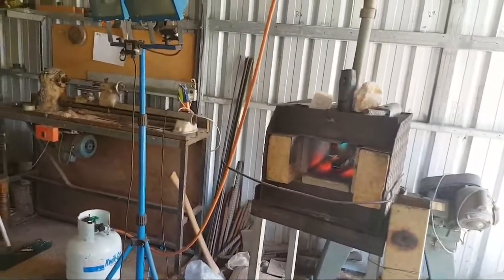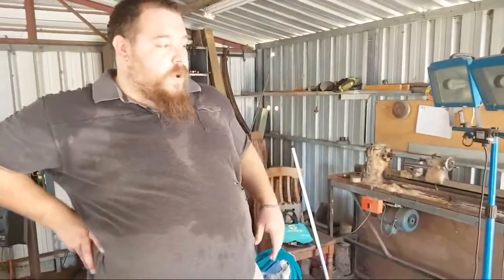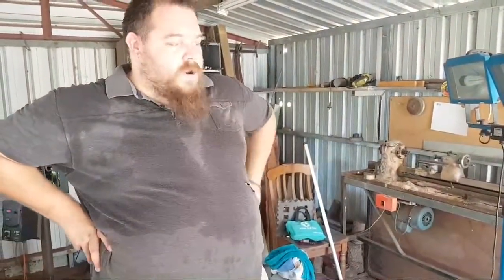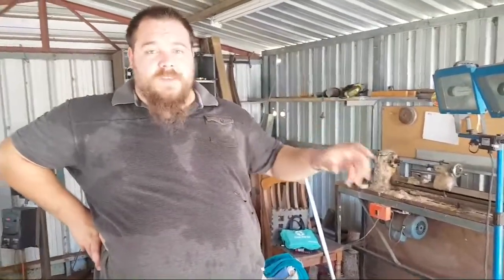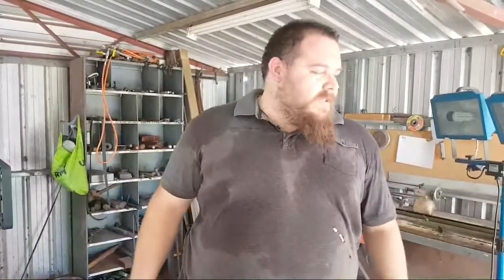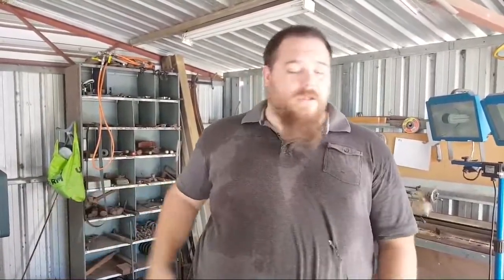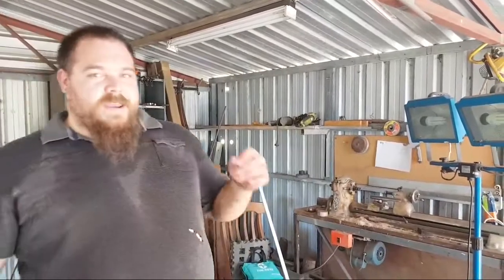And funnily enough, when you're doing forge welding in a gas forge, you actually want a rich flame as well, although running at a much higher temperature, in order to avoid decarb and also to avoid oxidization of the billet. Because if you're running a rich atmosphere, you don't need as much flux. It's the same idea as a neutral fire in a coal forge or a charcoal forge, that point in the forge where all of the charcoal is burning all of the oxygen up, and so therefore you're not oxidizing your pieces, which when you're forge welding mild steel, for instance, you don't need to use flux at all. You can get the same effect in a gas forge, it just takes a little bit more tricking around with it. Normally a good sign is either dull yellow or bright blue flames coming out of the front of your forge. If that's what's happening, then you're normally at a good neutral atmosphere.